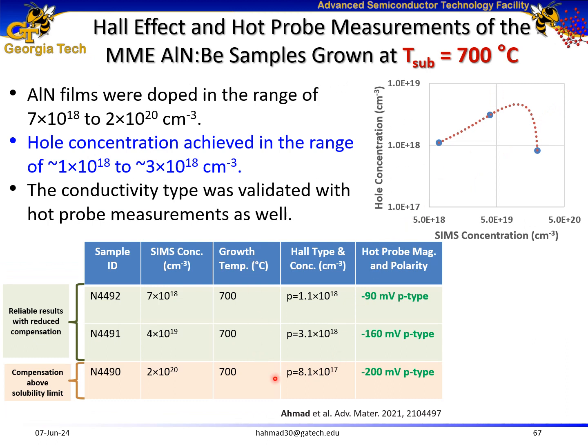I also grew beryllium-doped aluminum nitride at 700 degrees C growth temperature and achieved even higher hole concentration of 3 into 10 to the power of 18 per centimeter cube. And the conductivity type was also validated from hot probe measurements.